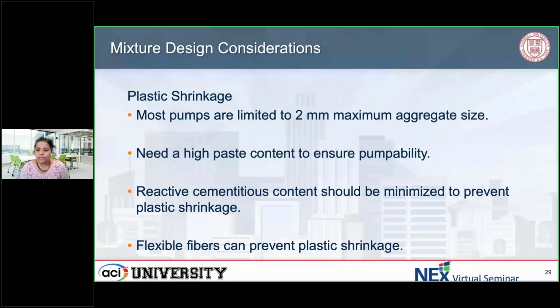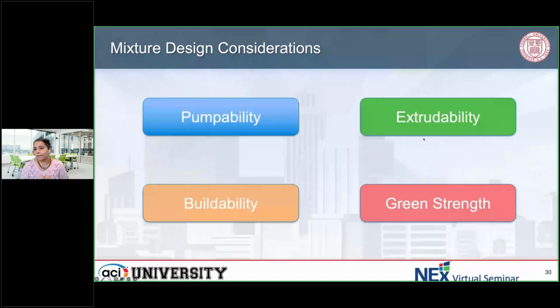So when you're thinking about your mixture, end of the day, you need to think about, can you pump that material? Will it stay uniform? Will there be segregation during pumpability? Which we already know a lot about because we're really good at pumping concrete. But in this case, it's not just about pumping the concrete, but the concrete that comes out of the nozzle needs to be extrudable. It needs to be able to hold its own shape and needs to be buildable. That means that you can do that layer by layer building so that you can achieve the height that you need. And to achieve that, you also need to have really good green strength, so that early strength as it's aging with minimum plastic shrinkage, so you're doing the least amount of damage to your designs.